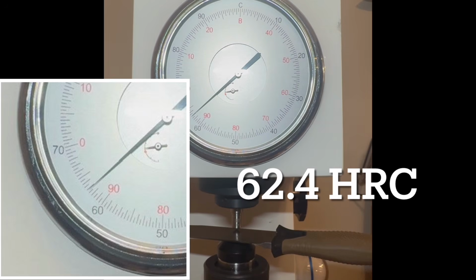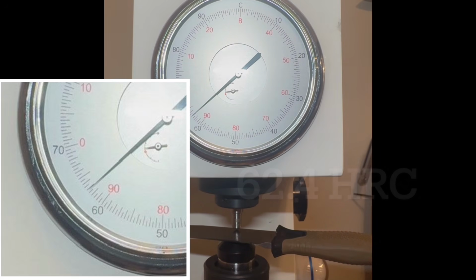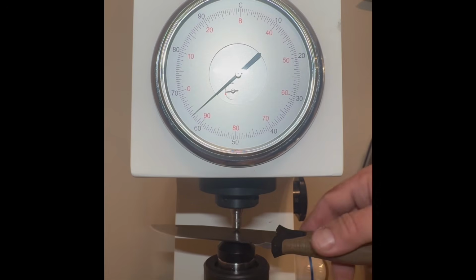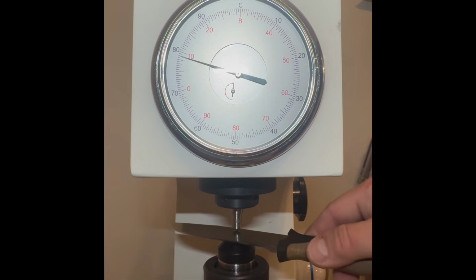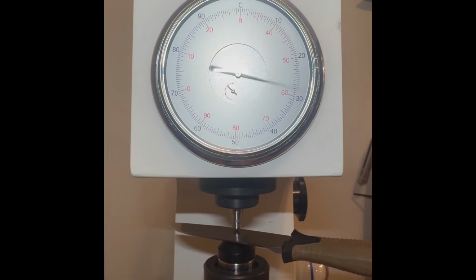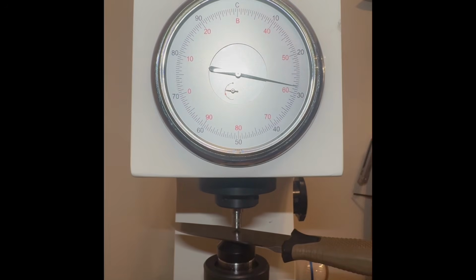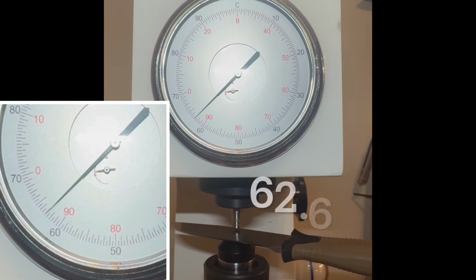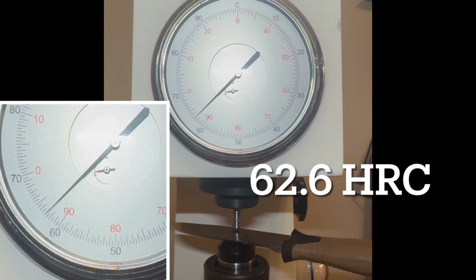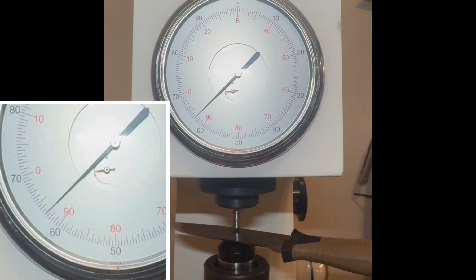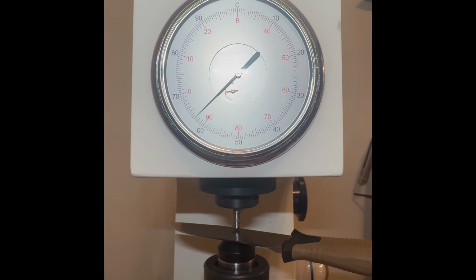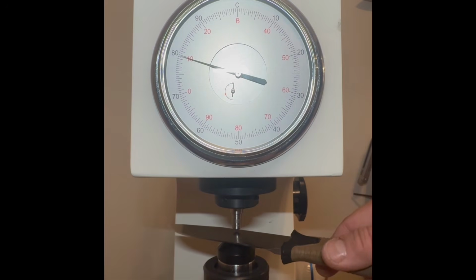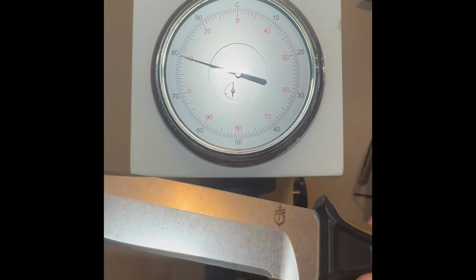This reading comes in at 62.4 HRC. The lab geeks call it a repeatable result, but please understand that I'm testing this one knife. Your knife may be slightly different from this one. And really, plus or minus 1 HRC doesn't make a huge difference in performance. And the third poke is at 62.6. Very solidly repeatable result. My final verdict is this blade is between 62 and 63 HRC.